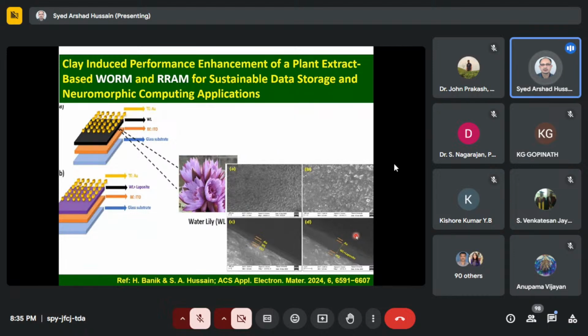And during organization, the orientation or organization of the organic material changes. Accordingly, their electric, electronic, and optical behavior changes. We have done a few works on how these organizations of material affect the optoelectronic behavior of organic material incorporated into clay. But here we incorporated clay in the active layer, that means within the plant extract in one case, and we have found that the presence of clay affected the device performance.